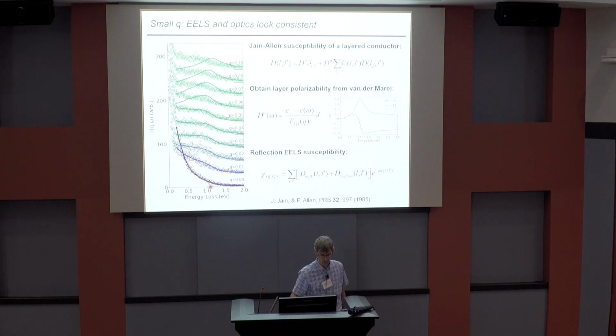You can see at small momentum, it agrees pretty well. And this dimple here comes about because there's a plasmon in the optics. At very low momentum, there's this tail here. It comes from the matrix elements in EELS, which at small momentum are very frequency dependent. But as you go to increasing momentum, you can see a shoulder there, and it agrees fairly well with optics.